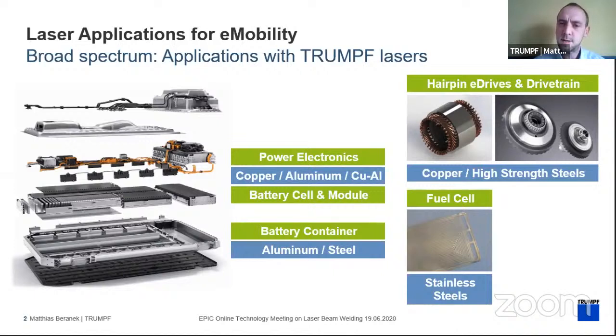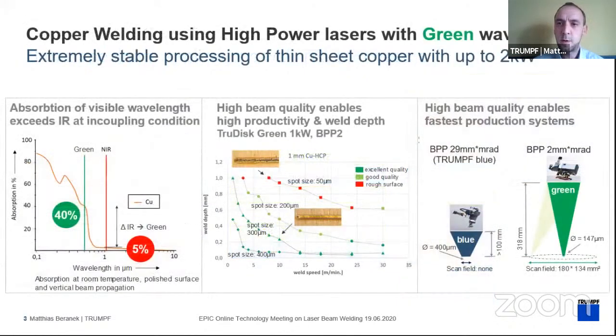What I think is that there is a huge shift from what we've seen in the past, like steel and aluminum welding, to mainly copper welding. So this is something we're looking particularly into. And for that, we have elaborated a whole new laser lineup, which are the green lasers based on the disk platform by frequency doubling. The reason for that being, as you can see here, absorption of copper in that green wavelength is 40%, so it's much higher than infrared. And this gives you much better handling of those welding applications.